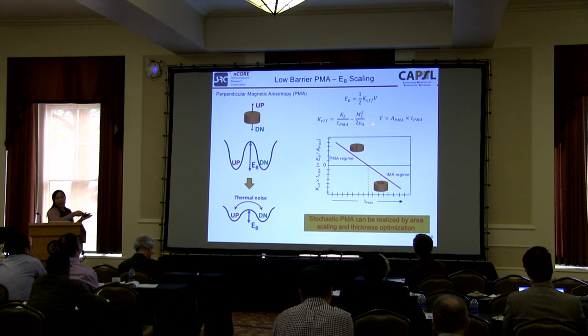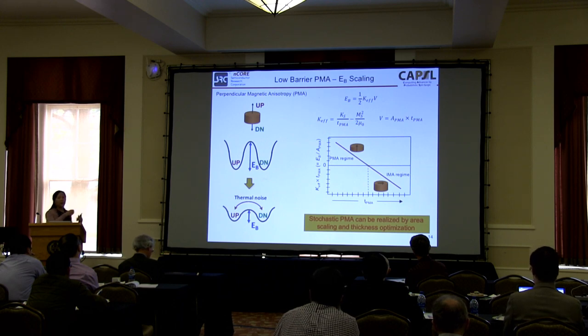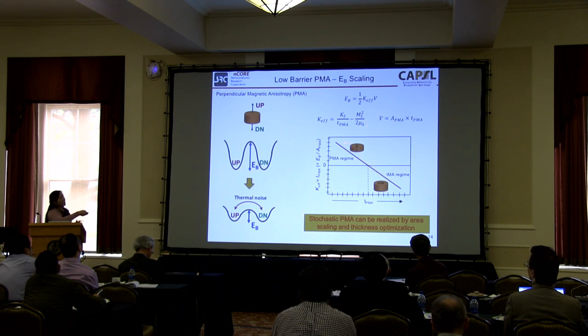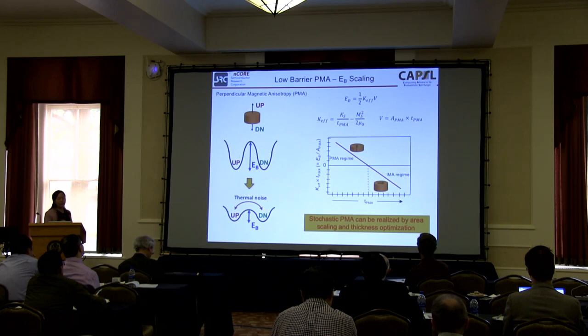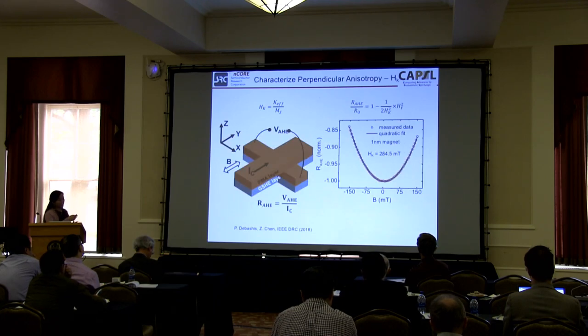For the normal IMA magnet, in-plane magnets, the first term is very small because my thickness is large. So the second term, the demagnetization energy, dominates. That's why my in-plane magnet always has in-plane magnetization. But for PMA, once my thickness becomes smaller and smaller, the first term can become really large, eventually even cancelling the demagnetization energy term. And that's when I can actually reach zero energy density by tuning the thickness of my PMA film. And that's basically what we do.